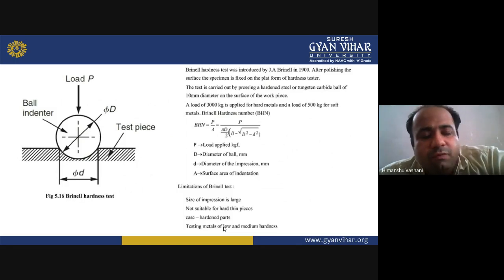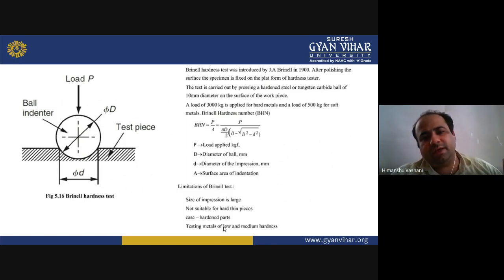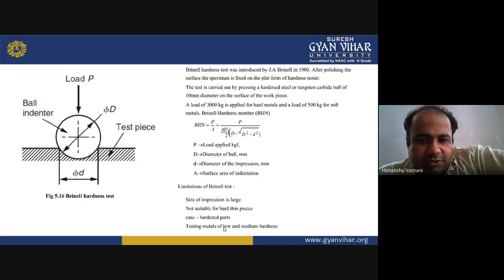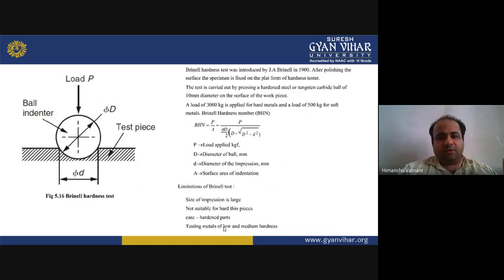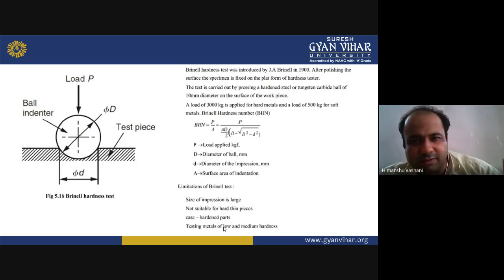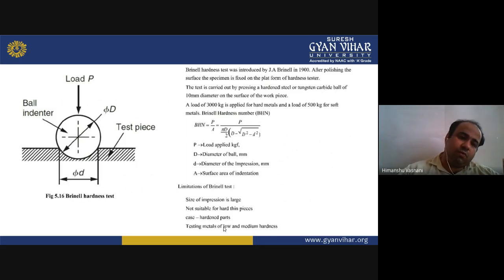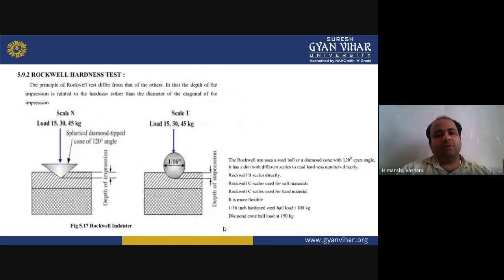You can see in the arrow where the load P is shown from top to bottom. This load is applied in kgf, capital D is the diameter of the ball in millimeters, and small d is the diameter of the impression shown in the diagram, also in millimeters. A is the surface area of indentation. Now the limitation of this Brinell test is that the size of the impression is large, and it is not suitable for hard thin pieces or case hardened parts. It is suitable for testing materials of low and medium hardness. Now this is the Rockwell hardness test.